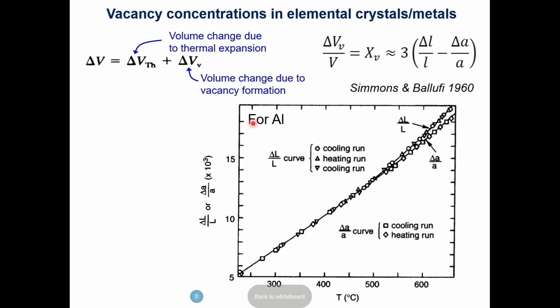You can see this is the data for aluminum metal. On this axis, what is being plotted is dimensional change and lattice parameter change as a function of temperature. At low temperature they overlap on top of each other, but as you go to 550 degrees or exceed 500 degrees Celsius, they start to diverge. This one is the dimensional change, and the lower one is the lattice parameter. The bigger the difference, the higher the amount of vacancy, because as you go to higher temperature, they diverge more and more since you're creating more and more vacancies.